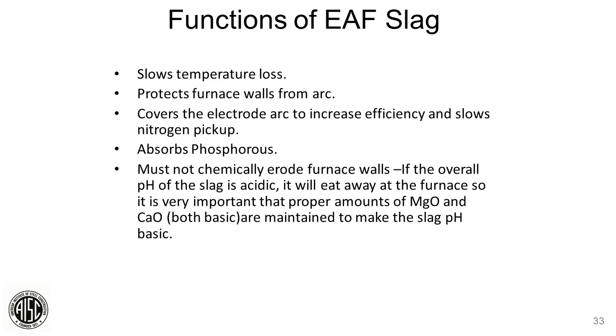The slag also, very important, absorbs the phosphorus. So this is where we get rid of the phosphorus in the steel, through the EAF slag and the oxidizing environment. It also has to be pH balanced, essentially, so that it doesn't eat up the refractory of the furnace. So we have to contain proper amounts of MgO and CaO, which are basic, to maintain the right slag pH. Next slide, please.